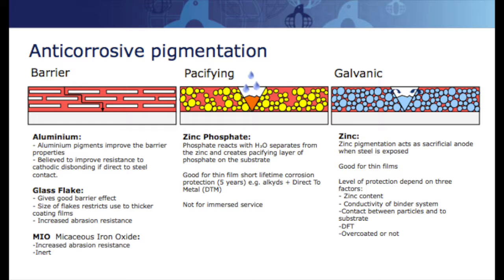It's a bit of an extra step when you go towards glass flake, because glass flake's going to give you some additional benefits. One thing is the barrier. The other thing is actually a certain amount of flexibility in the coating. So it gives a little bit. It can help with expansion and contraction due to heat, whether it's from daylight or from the process itself. It also has a tremendous benefit when it comes to abrasion resistance. And we see that just regular epoxy coatings, when you put in glass flake at the right sort of levels, you get a tremendous benefit in the way that it performs. So a glass flake is definitely a good upgrade.